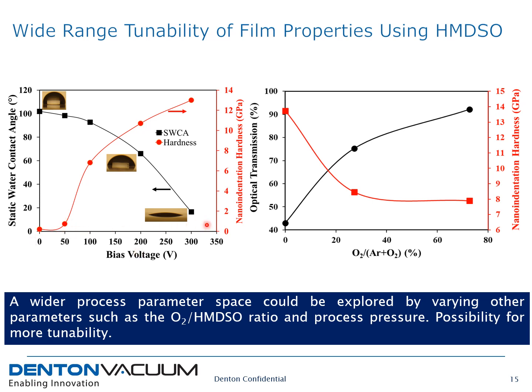So as the bias voltage increases, what you can see is that the nano indentation hardness changes from less than 1 GPa all the way up to about 13 GPa, and the water contact angle decreases from about 100 degrees to about 16 degrees. So you can actually tune the film from a polymer-like coating all the way up to a hard DLC-like coating. And also, in addition, you can see that the optical transmission can be changed by changing the oxygen argon ratio.